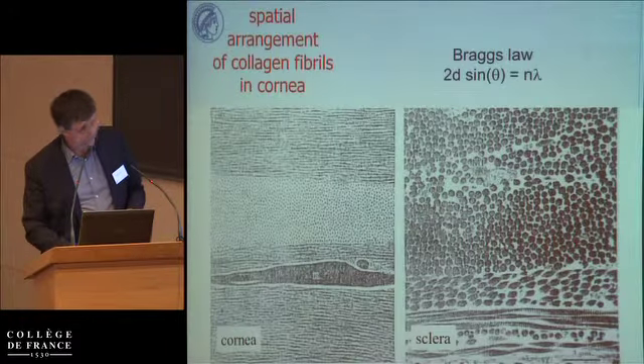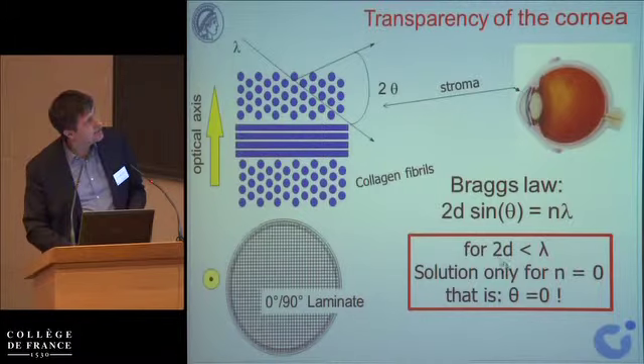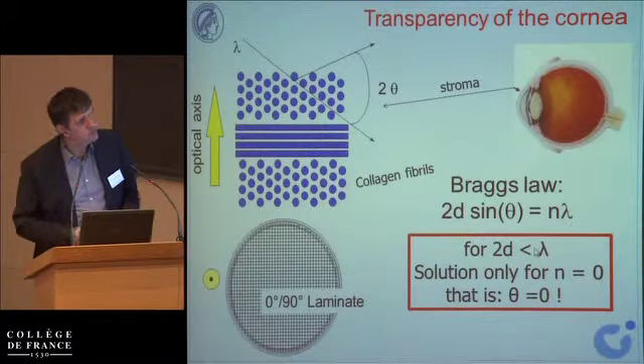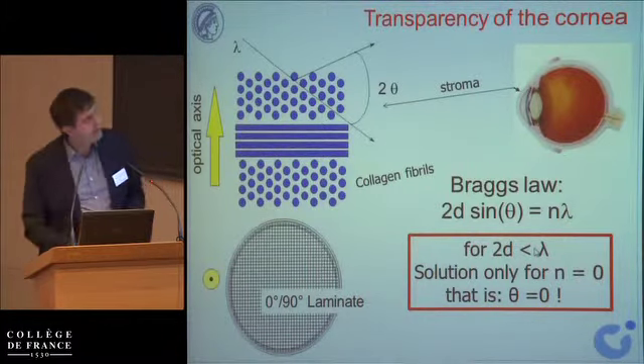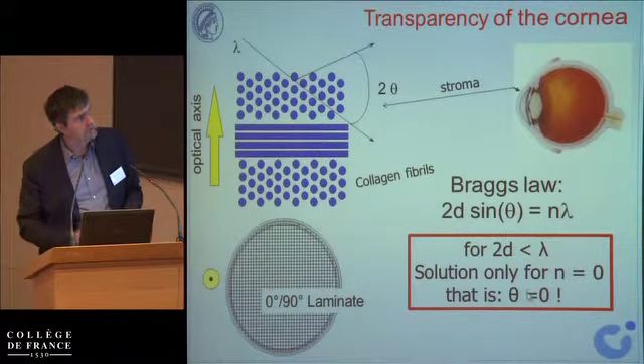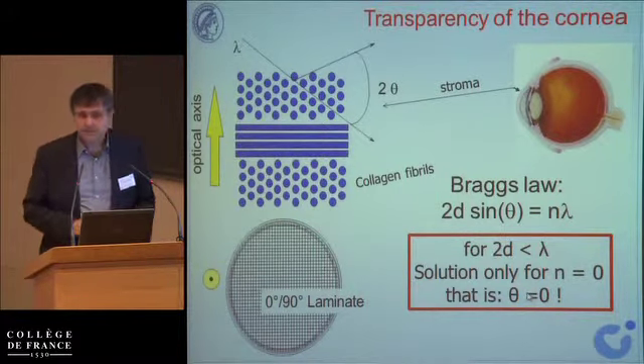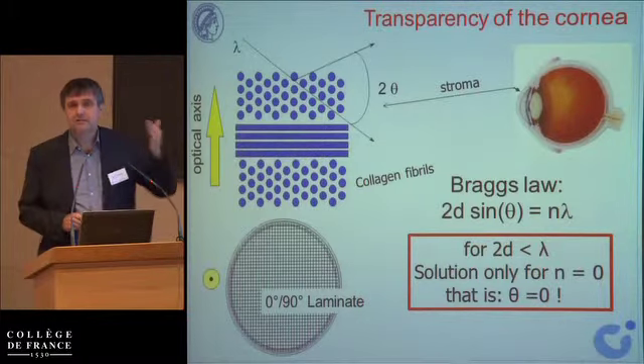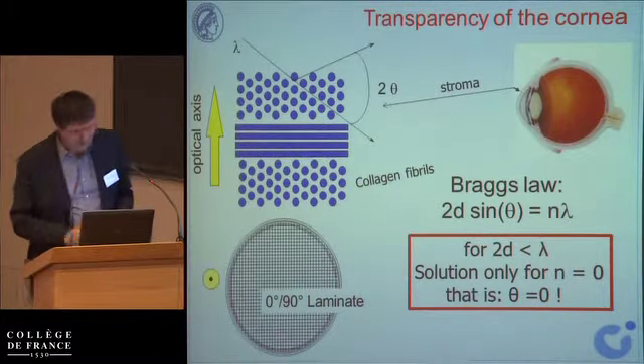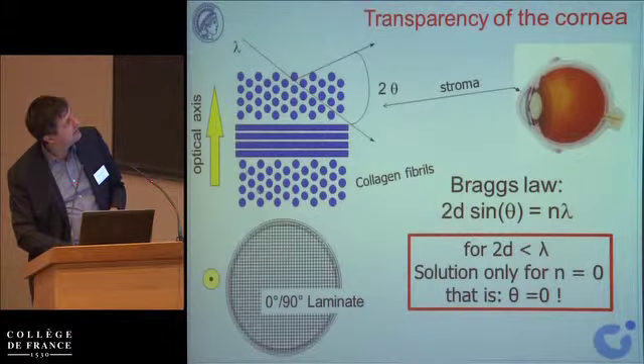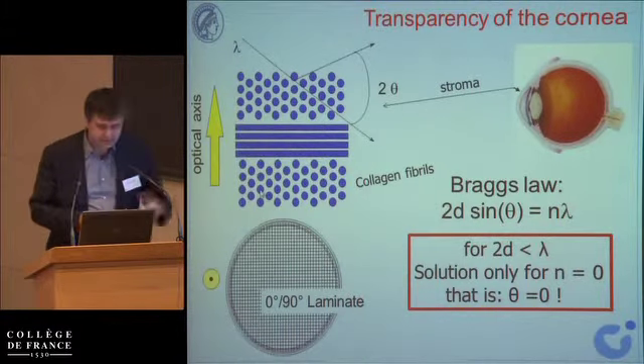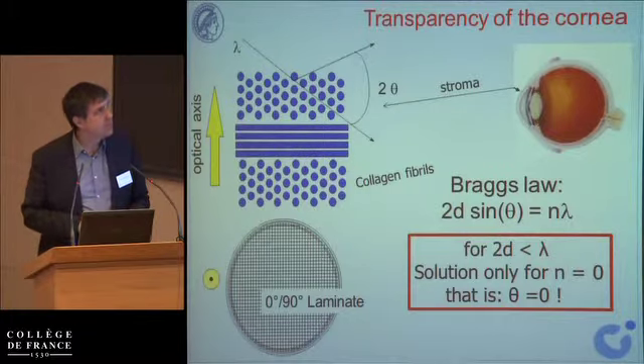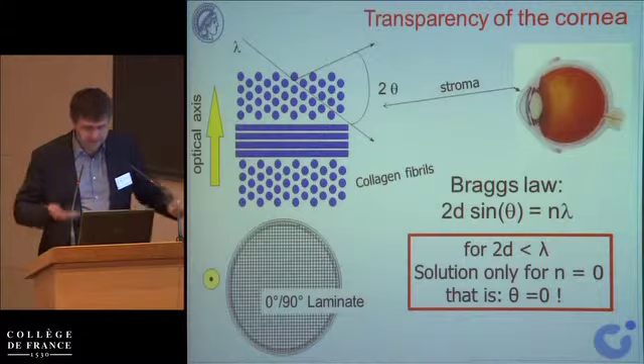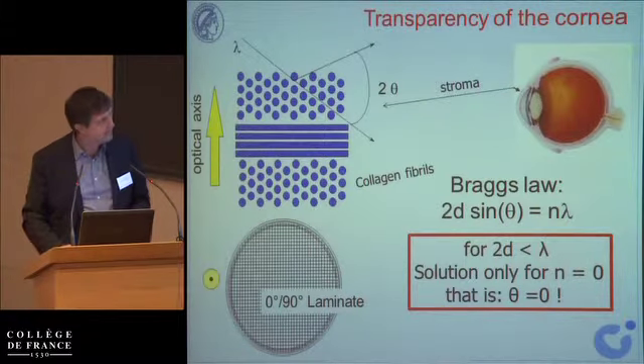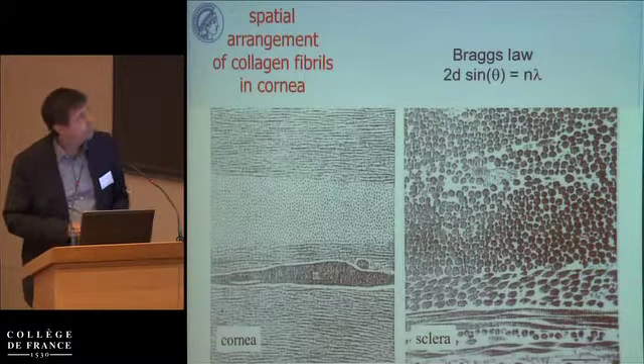So if I make sure that 2 times the distance between fibrils is smaller than the wavelength, then the only solution to that equation is for n equals 0, and therefore theta equals 0, so there is no diffraction. So basically, in a regular grating, if 2 times the spacing between the diffracting elements is smaller than the wavelength, there cannot be diffraction. So that's the principle of an optical filter. And this is exactly what occurs, actually.